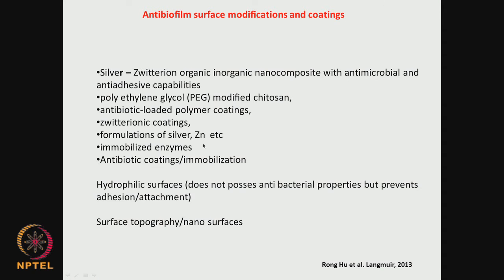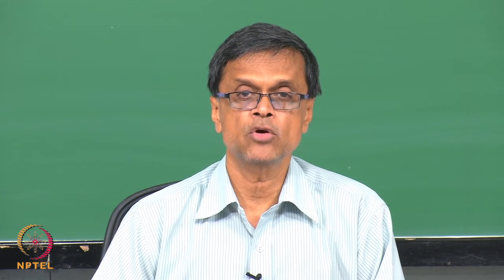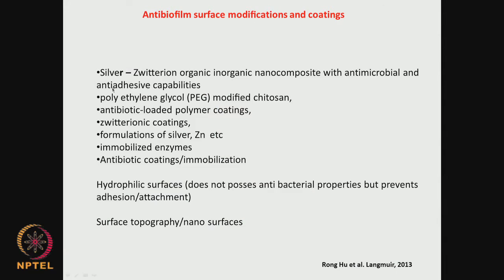So how do you eradicate biofilm? There are different approaches. One is to develop antibacterial and antibiotic coatings — slow-release systems, slow-release polymeric systems, or antibiotics immobilized or coated on the surface. Silver is quite commonly used because silver — in the form of nanoparticles, ions, or zwitterionic organic-inorganic nanocomposites — is known to have antimicrobial properties and also anti-adhesive properties. Anti-adhesive means the surface does not kill bacteria but prevents the attachment of microorganisms due to altered surface characteristics like altered surface energy or increased hydrophilicity.